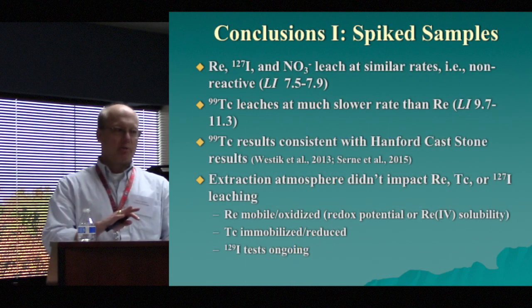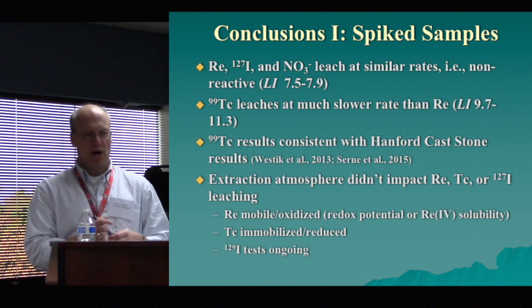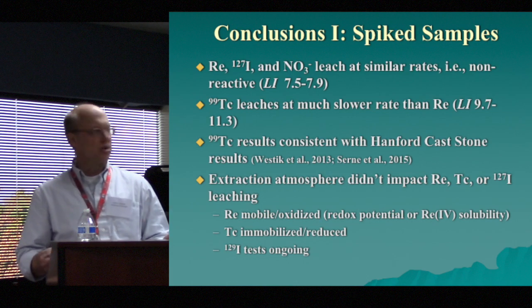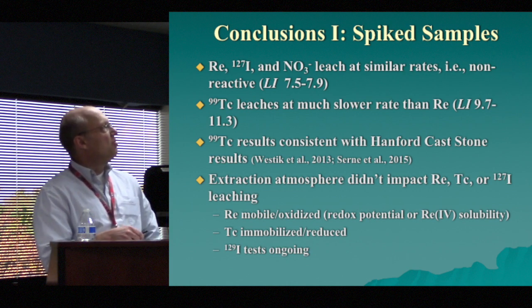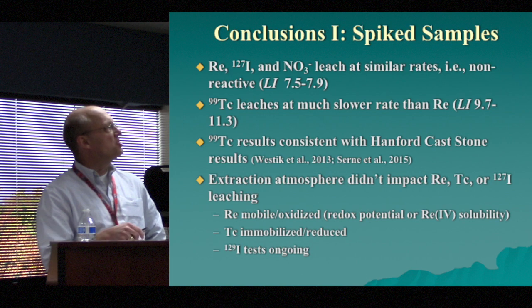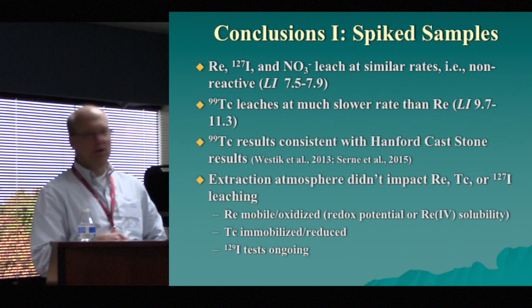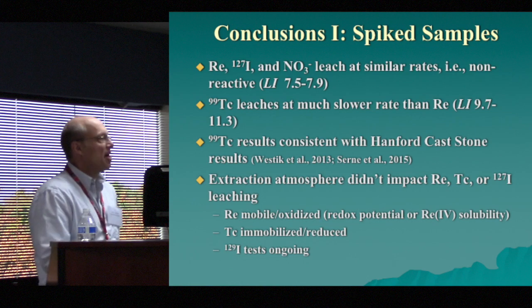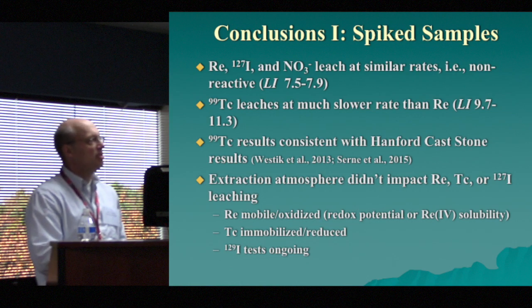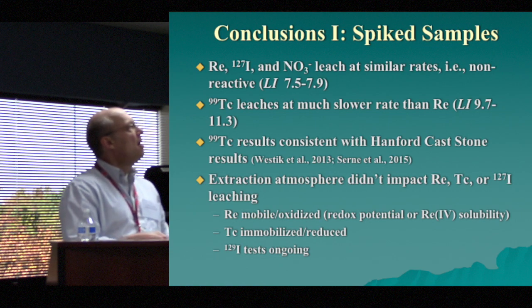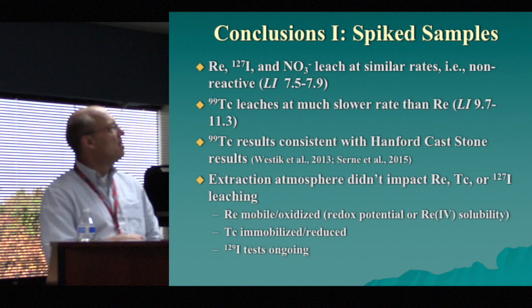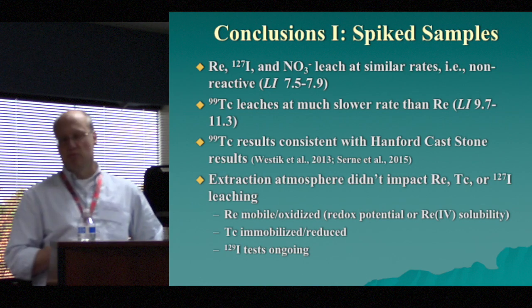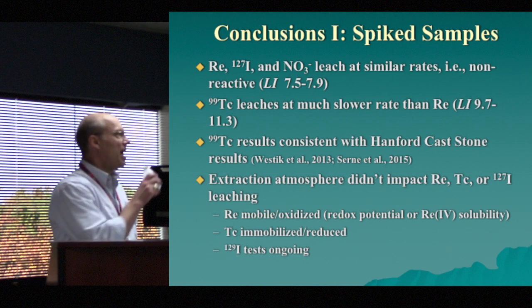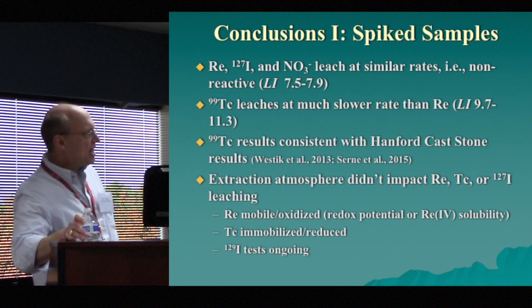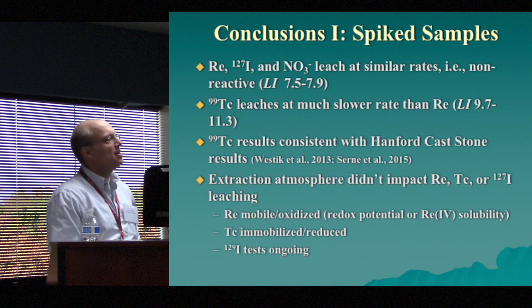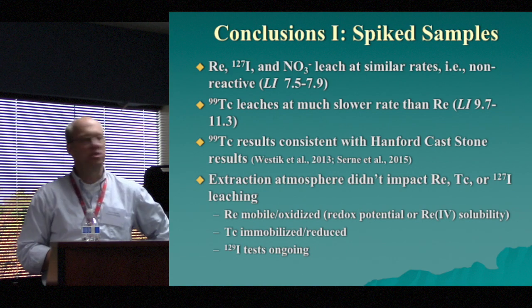So I want to briefly summarize some of the conclusions and then give you a little bit of background about what the next steps are going to be. So what we found is that rhenium, iodine-127 and nitrate leach at similar rates, and I used the term non-reactive. That's not actually the right term, but they have a much lower leachability index than Tc-99. Tc-99 leaches at a slower rate. The Tc-99 results are very consistent with what has been reported for the Hanford cast stone. The extraction atmosphere didn't impact rhenium, Tc or iodine-127 leaching at all.